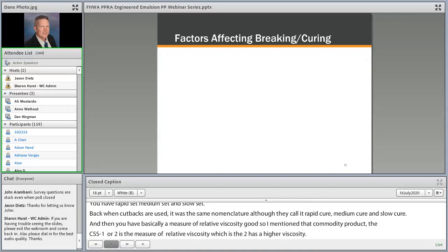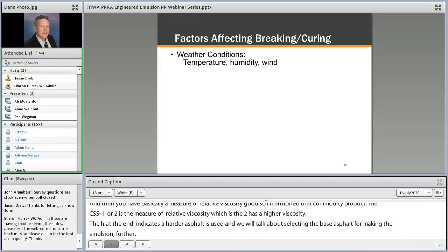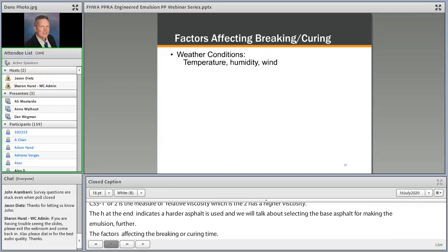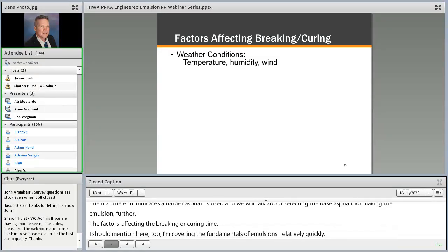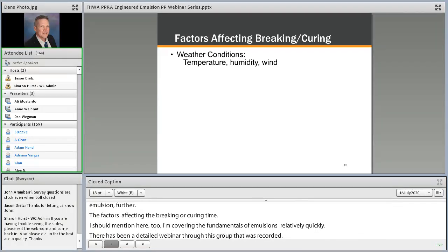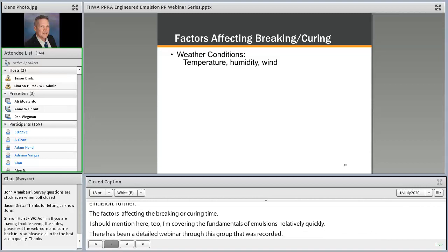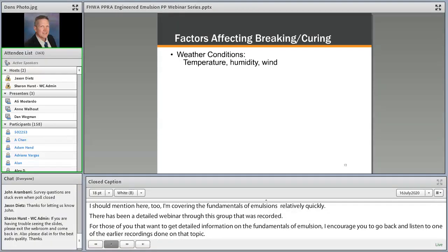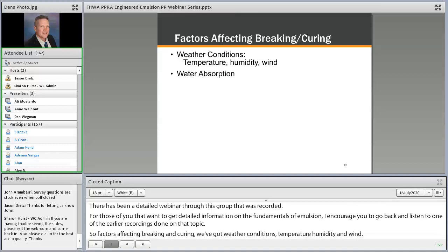So factors affecting that breaking or curing time. And I should mention here too that I'm kind of covering these fundamentals of emulsions relatively quickly. There has been a detailed webinar through this group that was recorded. And for those of you that want to get detailed information on the fundamentals of emulsion, I encourage you to go back and listen to one of the earlier recordings on that topic. So factors affecting breaking and curing, you've got weather conditions, temperature, humidity, and wind. Wind can be an awfully big factor at times. Water absorption into the aggregate itself.